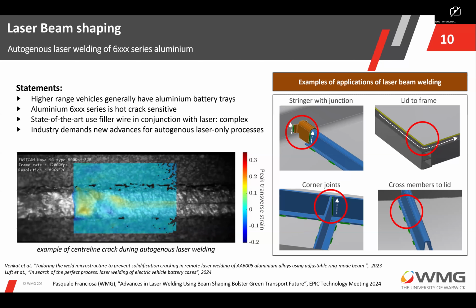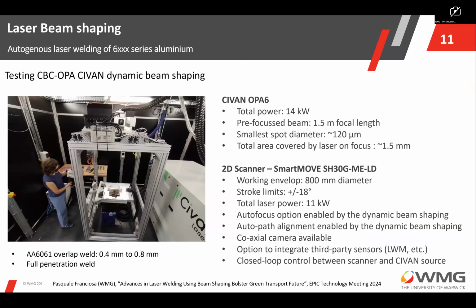But industry is eventually aiming, or it's like a wish list, to go away from wire and weld fully autogenous. So now this video is clearly showing a very nasty crack opening in the middle of the weld. It is a central line crack. The color map is showing the strain induced by the thermal load, and obviously because of the combination of the thermal load, the chemical composition of the alloy and the microstructure, you get cracks in the end. So it means those welds are not really functional.